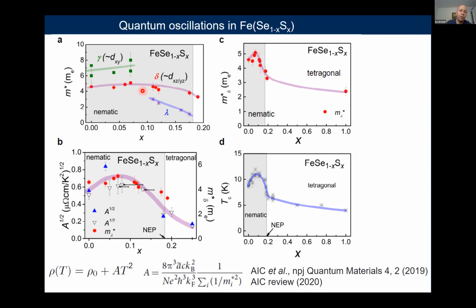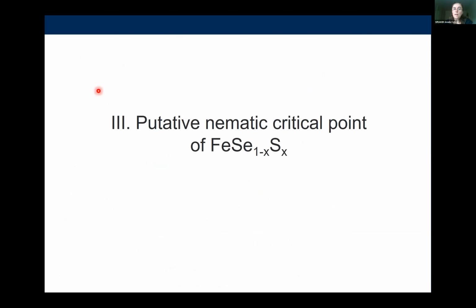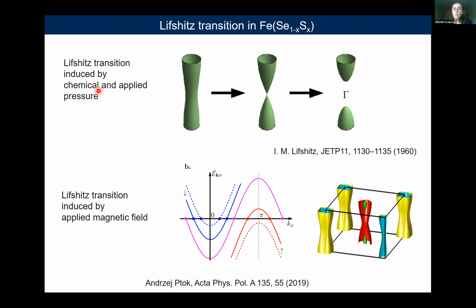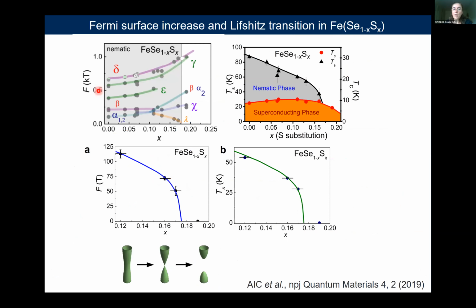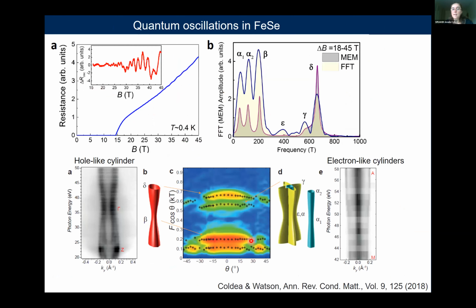But from the frequency, you can in principle also estimate the size of the pocket, but this you cannot really say. The size of the pocket we obtain in a different way, from the angular dependence. It's done here, so the gamma pocket is done here. And then you have to think about charge compensation, because it's a compensated system, how many electrons and holes you have to keep the charge compensated. Okay.